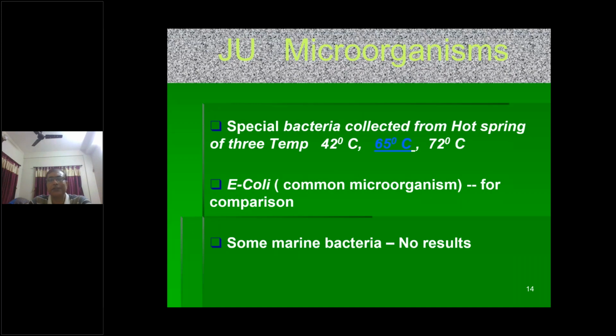But in our Jadavpur University, we have a special bacteria we collected from a hot spring very near Kolkata. Why did we choose a hot spring? It is well known that concrete is very hot at the initial stage. That is why we chose a hot spring bacteria. We also took some common E. coli bacteria for comparison, and also some marine bacteria. We noted that in these two cases we did not get any improvement. We chose 3 different types of bacteria at different temperature ranges: 42 degrees C, 65 degrees C, and 72 degrees C. Finally, we found that 65 degrees C is the most advantageous bacteria for our concrete.